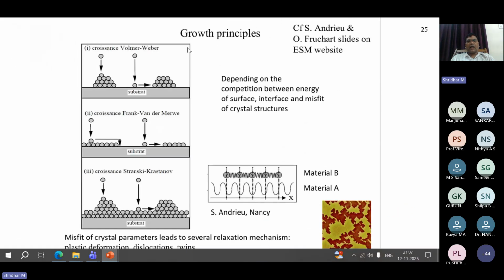You can see here I'm depositing. The gold atoms are coming, and it is just the same. Even if an atom falls here, because of this temperature it is pulled here, and it is going to form a thin, single layer of gold. If you want a second layer, then the evaporation rate should be increased, and that is why we say control is very important in these fabrication methods.